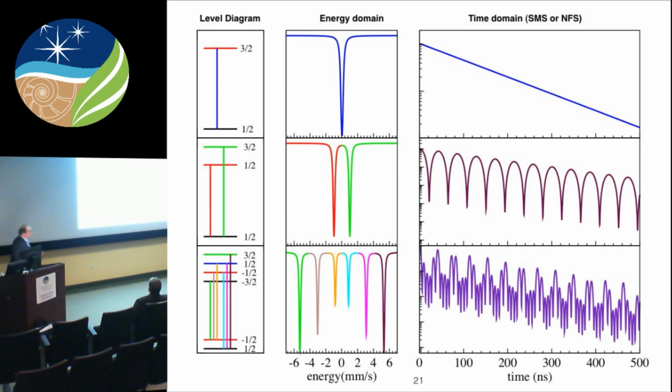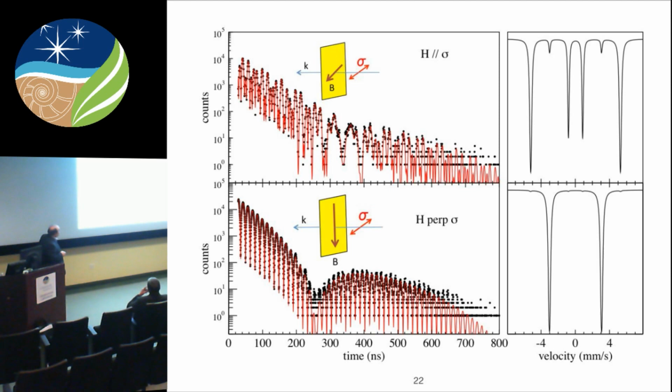So Ron was asking me today whether these transitions are sensitive to the magnetization direction. All right? So this was just for you, Ron. So here you see an iron foil. This is the polarization direction of the synchrotron beam, and this is the propagation direction of the synchrotron beam. If you make the field parallel to this, you will excite these four transitions. So obviously I didn't make it parallel enough, so I have still some little left, but I will get a pattern like this.